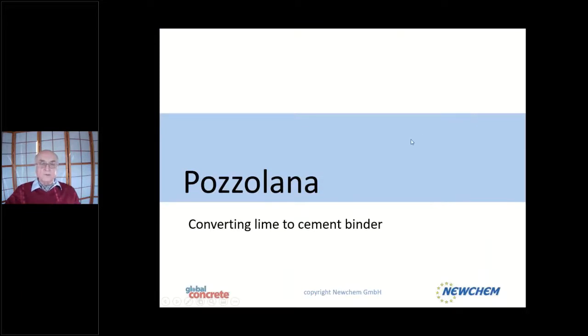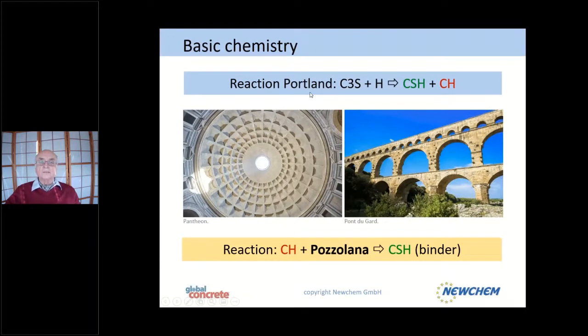So I start slowly with pozzolana. These are well known today. We are converting the lime to a cement binder. Normally in the Portland cement reaction, you will get about 25% of free lime when you use a CEM I, and this can be reacted. The Romans, already building with lime in the past, found out that if you added pumice or the fly ash from Vesuvio to your lime, you would get a bigger amount of non-soluble binders, as you have here in the Pantheon, which stands there for almost 2,000 years.